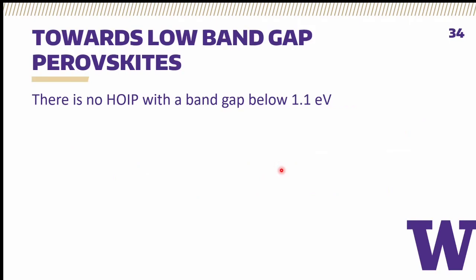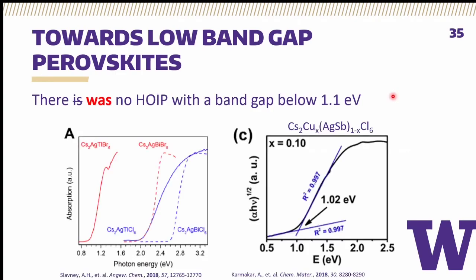So alternatives are considered, and we did a little bit of work to try to consider some of these alternatives. And we wanted to do so by challenging that very first precept I talked about in the design of perovskite-CdTe tandems, the idea that there is no perovskite that has a band gap below 1.1 eV. Indeed, there is no perovskite that has been employed in a solar cell with a band gap that low, but halfway through this process of working on these previous results, several papers came out in the double perovskite single crystal community showing that we had several different materials that had band gaps in the 1 eV range or below.